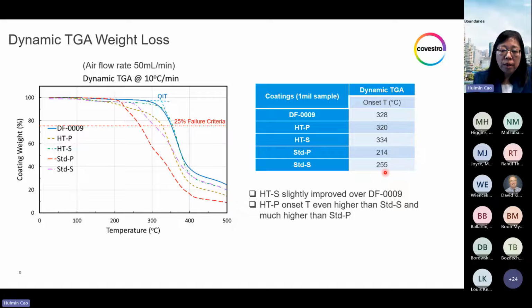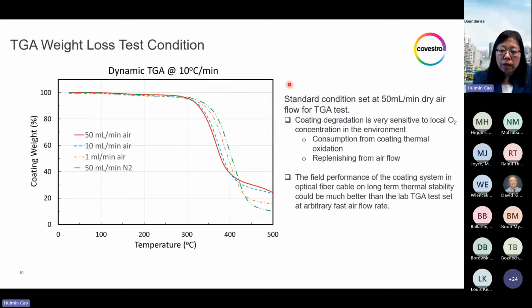One thing to notice is the test condition here: an airflow rate of 50 milliliters per minute for this TGA test. This is an arbitrary test condition set for TGA experiments. As in this comparison, you can see the air or nitrogen condition varies a lot on the weight loss behavior, which is understandable because the mechanism is highly involved in thermal oxidation. But also notice, even if all in airflow condition, the rate of the airflow makes a difference too. The higher the flow rate, the lower the onset temperature.